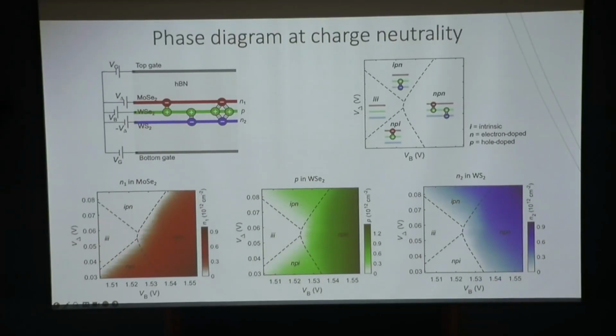And again, to know what's going on, we read out the electron density of the top layer, the middle layer and the bottom layer. Here you can see that the top layer is doped in this range, the bottom layer is doped in this range, and the middle hole layer is doped in this range. It actually matches the expected phase diagram.